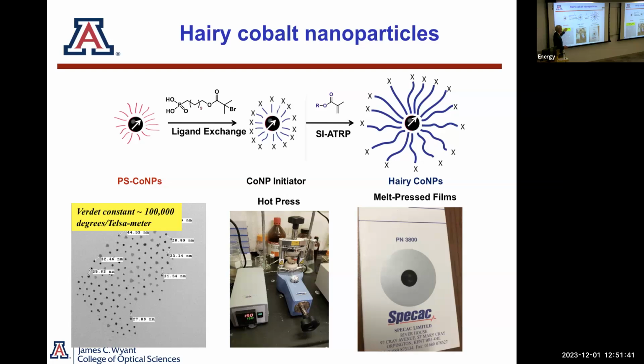So the magneto-optic properties of cobalt and any kind of ferromagnetic or superparamagnetic system are very interesting, but I often have to work with some very fragile crystal to do that. So if you can make a nanoparticle and incorporate it into a polymer, maybe you can come up with a system that's easier to process. This is work in collaboration with the Pyun group again, where they've made nanoparticles in the range of 15 to 30 nanometers in size.